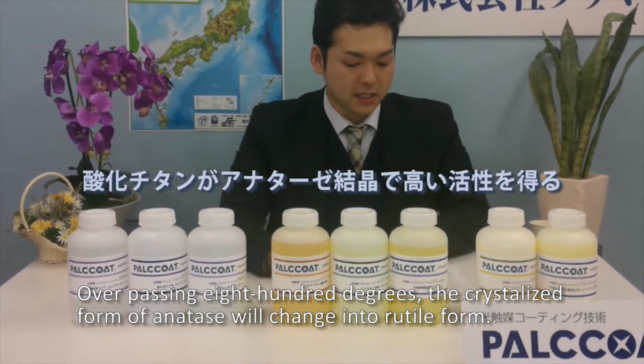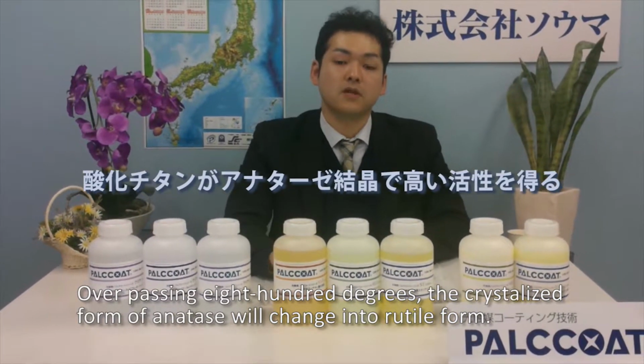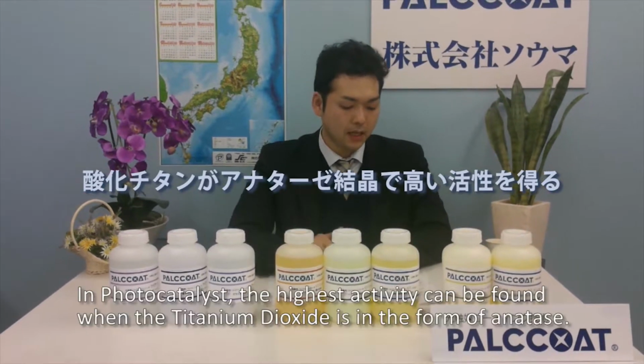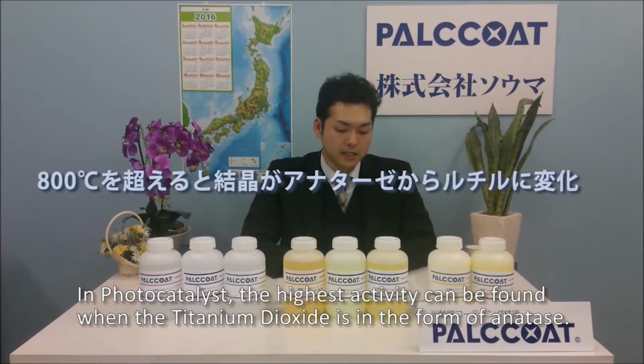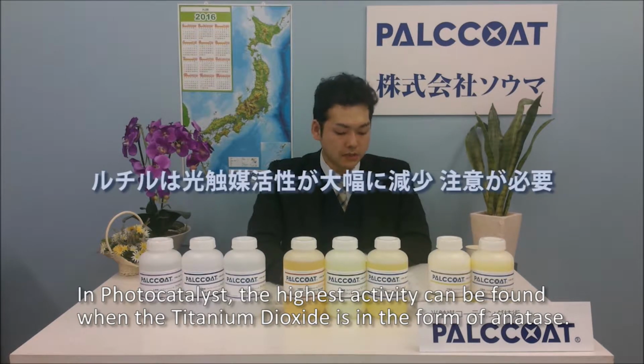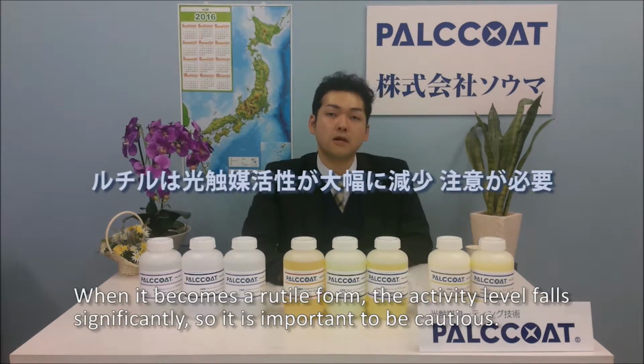Overpassing 800 degrees, the crystallized form of anatase will change to the rutile form. In photocatalyst, the high activity can be found when the titanium dioxide is in the form of anatase. When it becomes the rutile form, the activity levels fall significantly, so it is important to be cautious.